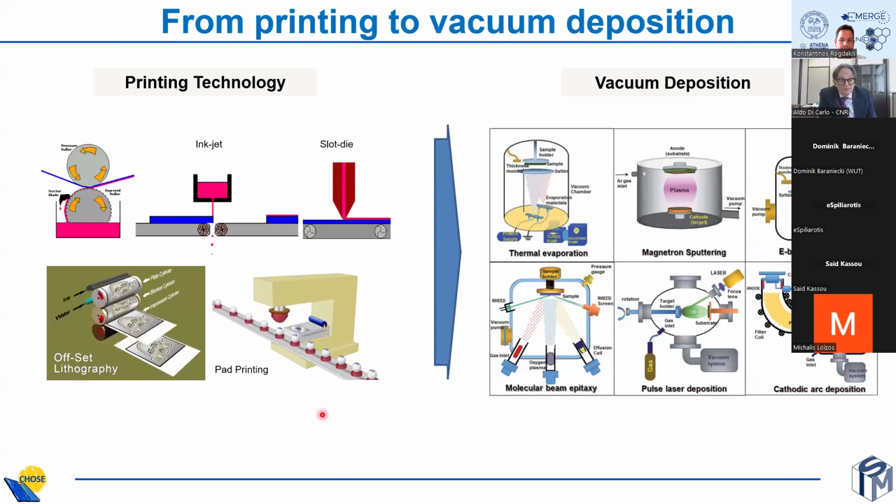For an absorber it is very critical because you need some thickness. You need at least 300 or 400 nanometers. Maybe a bit less in the case of molecules, but I believe for this kind of material, even with a direct band gap, you need 300, like in the case of perovskite. So compared to 2D thickness, 300 nanometers is a thick layer, so maybe it's not very convenient.